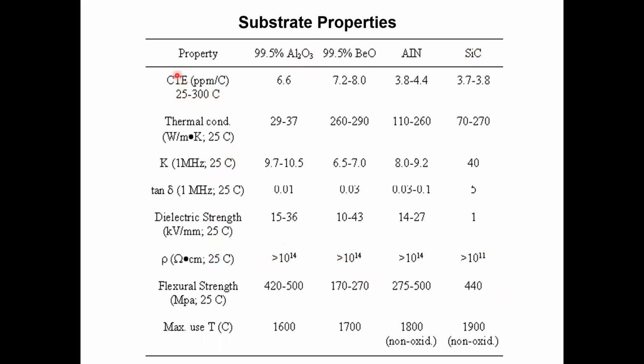The other considerations are obviously coefficient of thermal expansion, and silicon carbide will have a better match with silicon technology compared to some of these oxides. But thermal conductivity wise, some of these materials are more attractive than alumina, but alumina is still a material of choice because of the cost. And you can make alumina inexpensively in bulk form, like sheets of alumina, using the so-called green tape casting technology. Whereas beryllium oxide is not desirable from the environmental point of view. It's a health hazard.